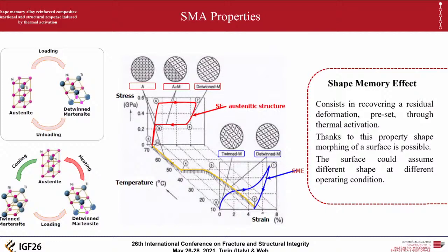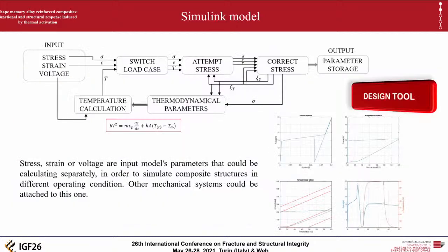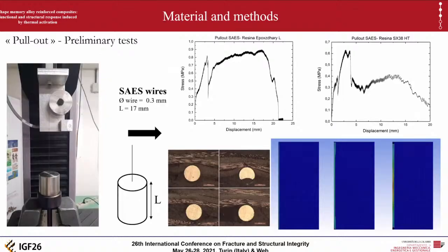It consists in the recovery of residual pre-deformation downstream of a thermomechanical training. To design and simulate the complex SMA's behavior, a design tool was built. Starting from Brinson's work, a thermal model has been introduced to simulate the joule heating. The idea is to simulate the interaction of complex systems with the SMA components. For example, pull-out tests have been carried out in order to simulate the SMA wires adhesion to solve the problem